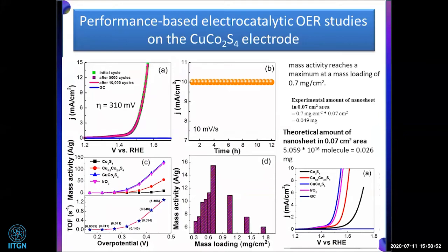You can see it is in 2017, and the overpotential η was 310 millivolt. At that time it was very low. And it is giving constant performance for 12 hours, and 10,000 cycling also. And it gives a mass activity which reaches maximum at a mass loading of 0.7 milligram per centimeter square.